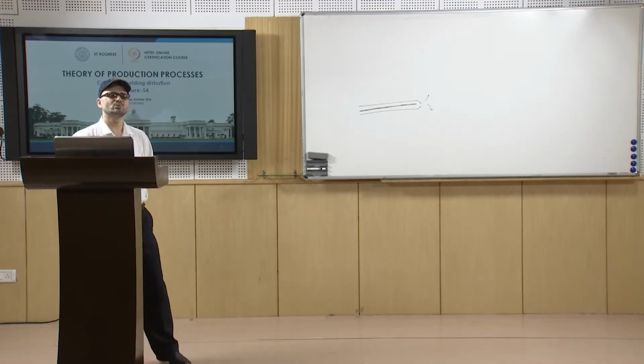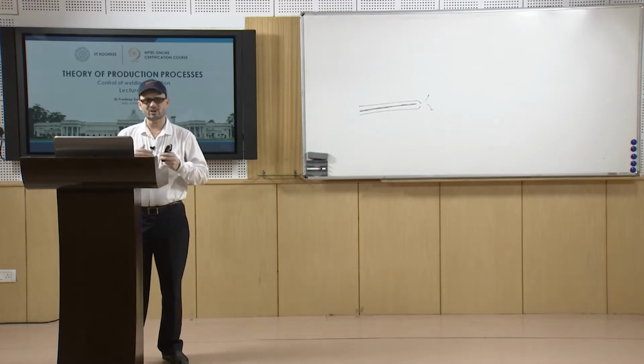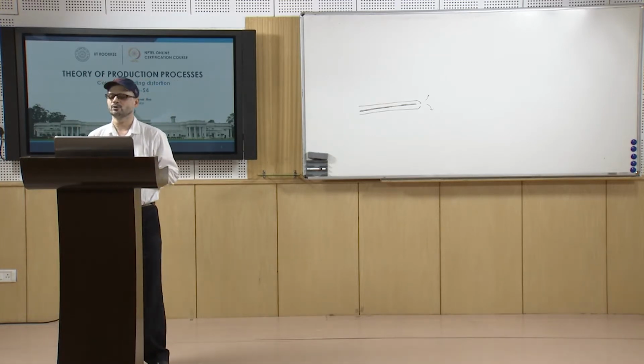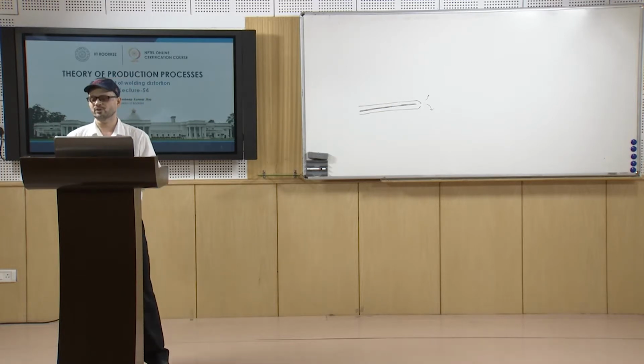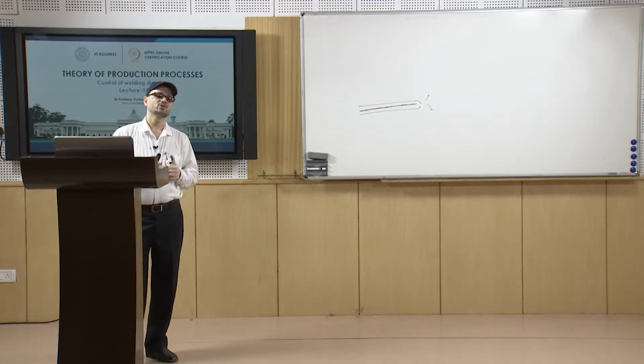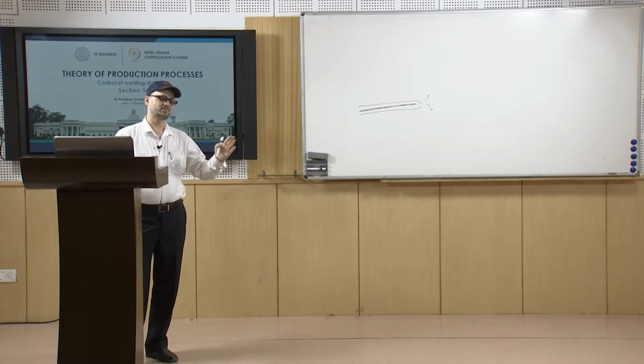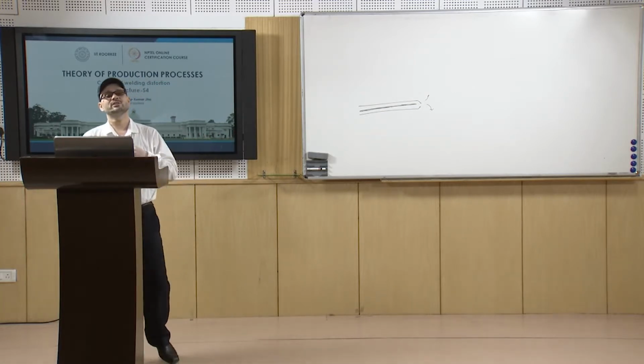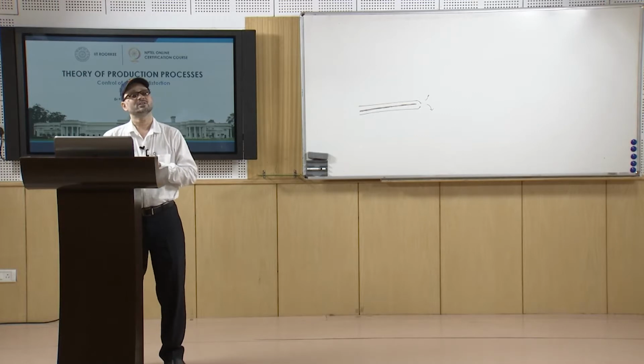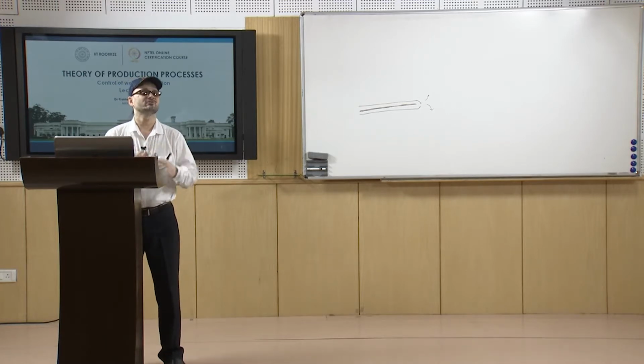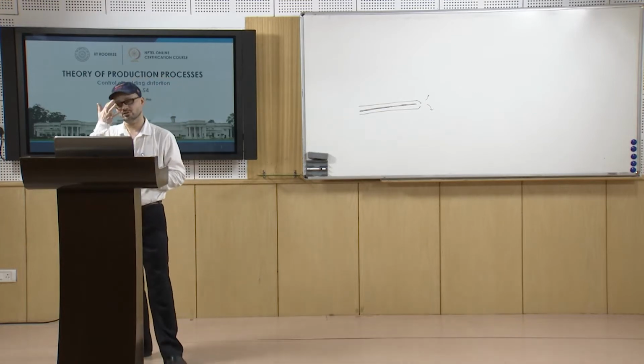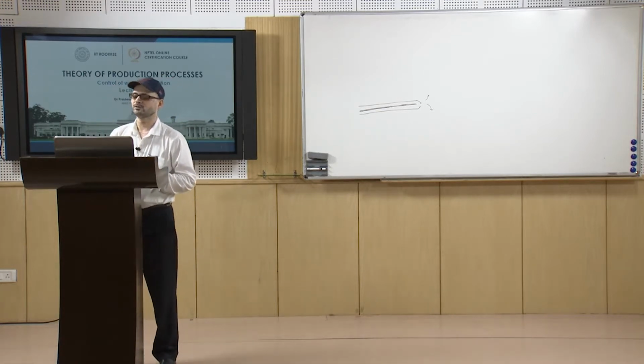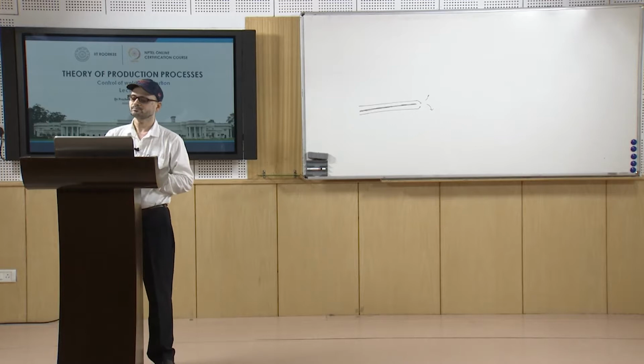So, what we do normally is that we preheat the material before tacking. We preheat the plates, so that when we tack, the heat extraction rate will not be that fast, and it will avoid any kind of hardness or cracking during that process.